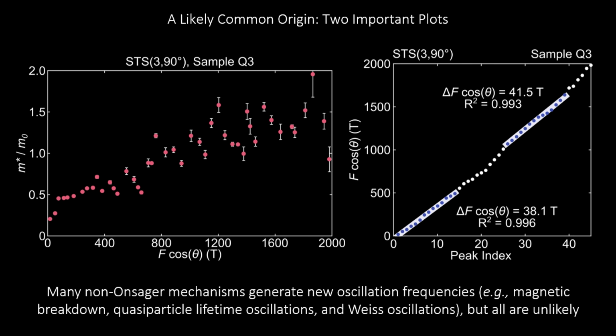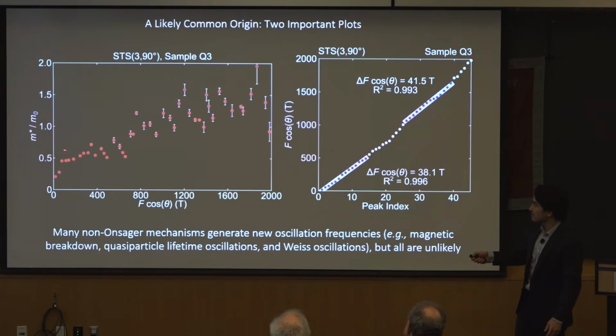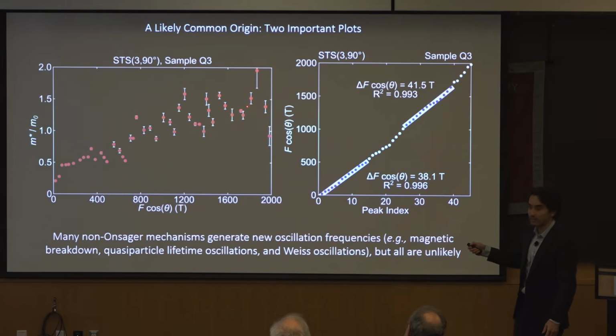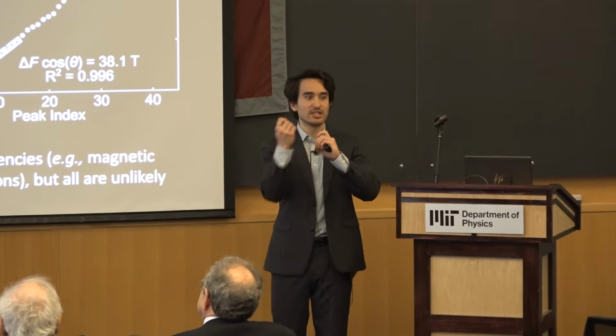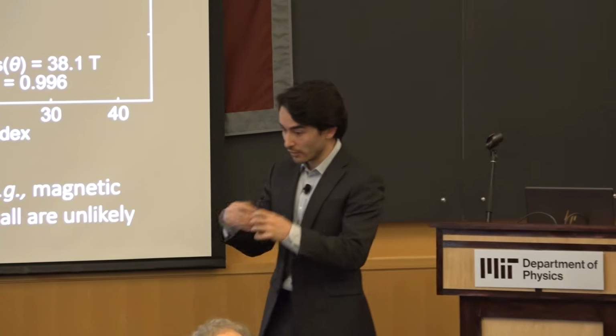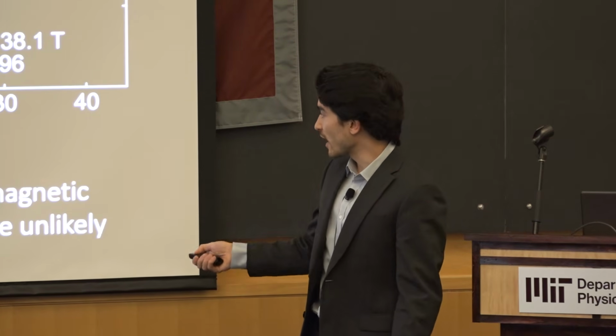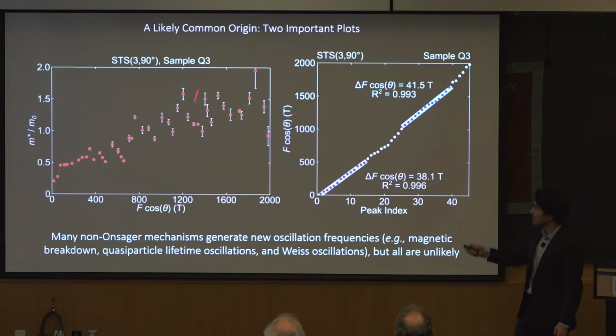So to explain perhaps a complicated Fermi surface, a complicated Moiré metal, we would think that maybe the effective mass, so the temperature dependence of quantum oscillations, might isolate this. Here's a plot of the effective mass normalized by the bare effective mass as a function of the frequency of the peak that we observed. You can see that it's roughly slowly varying essentially. With magnetic breakdown, typically I'd have two Fermi pockets very close to one another, and at high fields I can tunnel between these Fermi pockets and enclose the composition of those pockets. So from magnetic breakdown, we would expect this structure to skyrocket up to 45 bare effective masses or plummet down to 1/45. It is increasing, but at a very, very slow rate as a function of many, many frequencies.